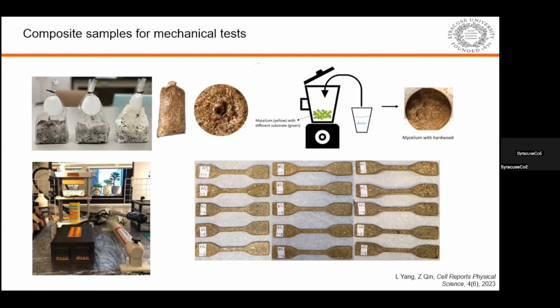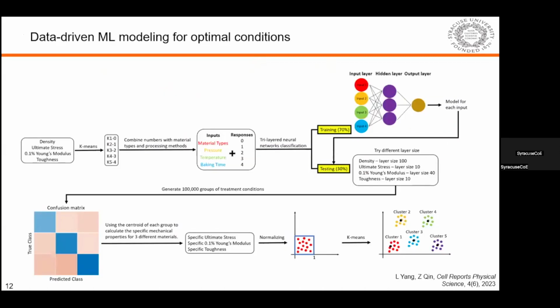And we do mechanical tests on each of those dog bone samples. And we analyze the results, and we build a machine learning model based on that to classify the strength, toughness, and the Young's modulus of these dog bone samples. And we correlate those mechanical performance to the treatment process. Like during the heat press, we have the temperature under control, we have the amount of time under control, baking time, and also the pressure under control, as well as the material, the substrate type.